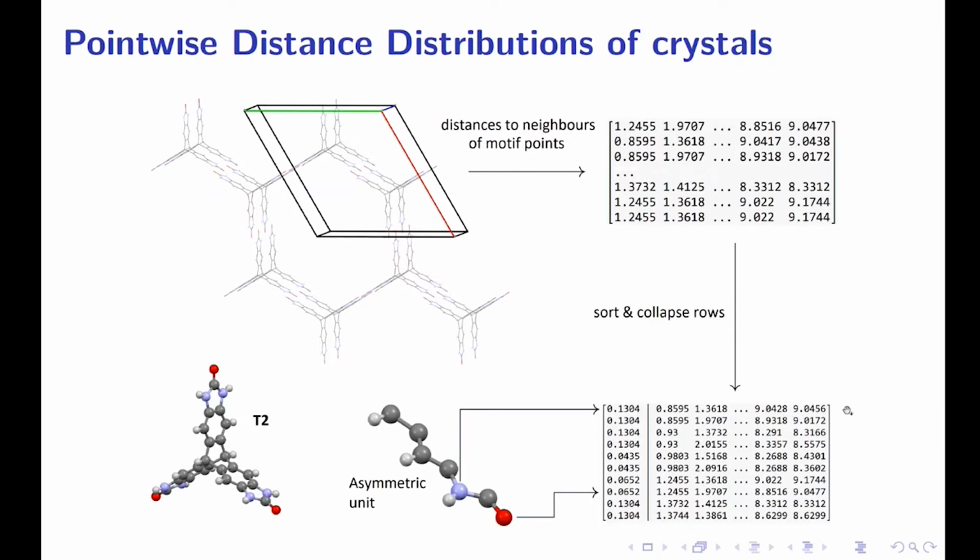So I should mention that in the finite case, the number of columns was 3 because there were only 4 points. But now we have infinitely many points to measure distances to. We just have to choose some cutoff value. And I think here I chose 100, which is pretty typical for us. So an atom's 100th nearest neighbor is going to be around 9 angstroms away.